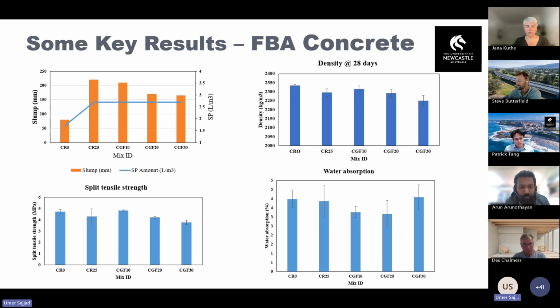So we have slump value first of all. The slump of the furnace bottom ash concrete mixes is slightly higher. You can see here, but why is it higher? As the water absorption of the furnace bottom ash is higher, we have used an additional amount of superplasticizer to make it more workable. Otherwise, when we did the preliminary testing, we found that with a lower or similar amount of superplasticizer as control concrete, we get a harsh mix, which is very difficult to work with and very difficult to place.